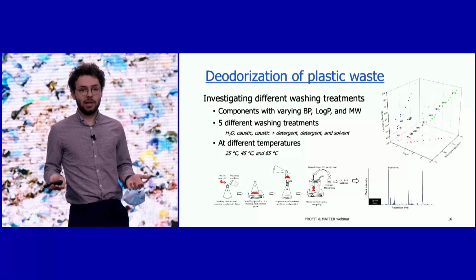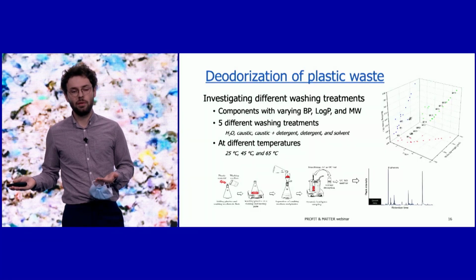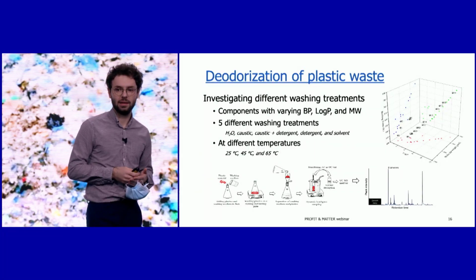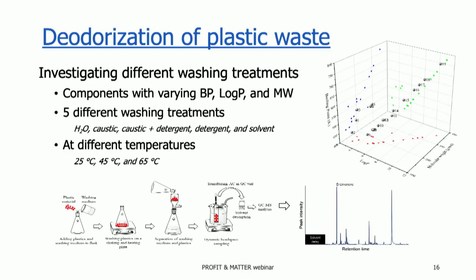Our next step was to investigate more fundamentally the deodorization of plastic waste. For this, we first selected 19 odorous components that have a varying boiling point, octanol-water partition coefficient, and molecular weight. We applied 5 different treatments, namely water, caustic soda, a combination of caustic and a detergent, only a detergent solution in water, and a solvent. We performed our analysis at 3 different temperatures, namely 25 degrees Celsius, 45 degrees Celsius, and 65 degrees Celsius.